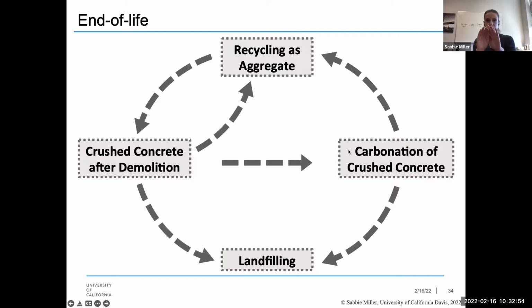Basically, by increasing the surface area to volume ratio of our concrete, we can facilitate carbonation, potentially occurring at a faster rate. Of course, it still needs to be under appropriate conditions, moisture, temperature, et cetera, exposure to atmospheric carbon dioxide. It can't be buried under other concrete, but that also can act as a mechanism that facilitates lowering of an overall environmental footprint associated with the material, as long as there isn't harmful leaching. And then, of course, there's always the potential to landfill the crushed concrete, but that typically is not the most environmentally desirable option.